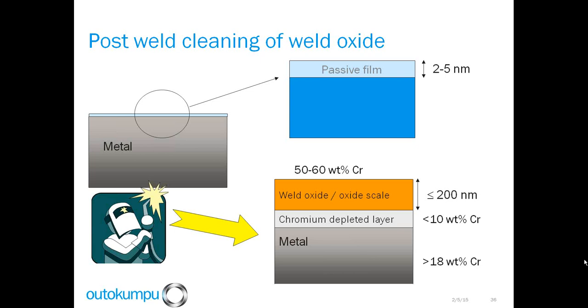And why do we want to remove these heat tints? Basically, if you look at stainless steel before welding, you've got a passive film that's 2 to 5 nanometers thick that is enriched in chrome oxide. That basically protects the material, keeps it corrosion resistant in stainless steel.